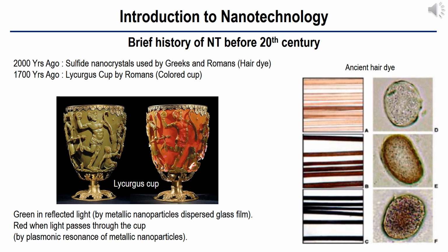The Lycurgus cup has now assumed an almost iconic status in the nanomaterial field as an early example of the surface plasmon phenomenon, in which waves of electrons move along the surface of metal particles when light is incident onto them. Analyses have demonstrated that the glass in the Lycurgus cup contains rather small amounts of gold powder embedded within it, on the order of 40 parts per million. These tiny metallic particles suspended within the glass matrix have diameters comparable to the wavelengths of visible light. As a consequence, a form of plasmonic excitation can occur, an oscillation of the free electrons at the surface of a metal particle at a certain frequency.